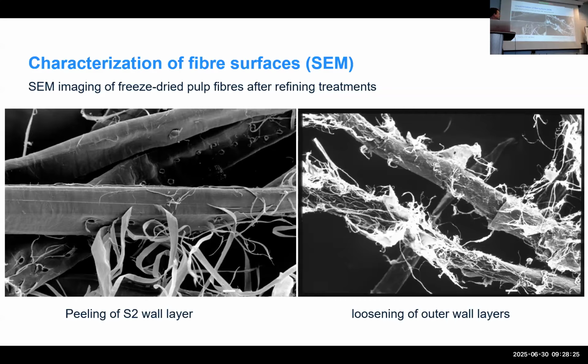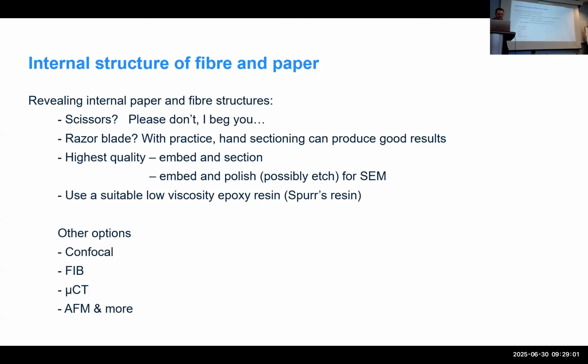despite having been coated. And then on the right, you can see other fibers where the outer wall layer is still here. There's the underlying secondary wall. But this outer wall layer, because of that crisscross arrangement of fibrils, when you put mechanical energy into it, kind of stretches out. And that's what we see here. It's been loosened from the fiber surface. That's what we call fibrillation, a term you'll hear in pulp and paper all the time. It has implications in interfiber bonding and paper strength.